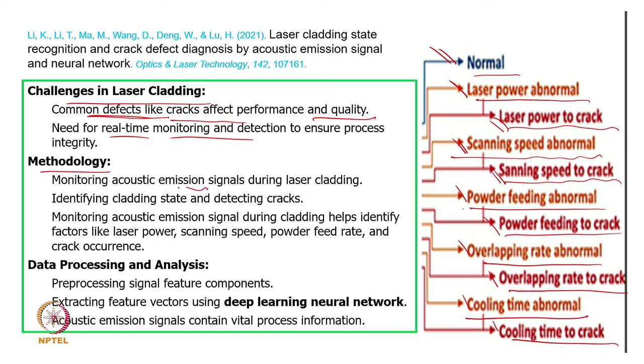Basically, we try to capture acoustic emission signals, and then based on that we divide into two categories. One is detecting cracks. The other is the cladding state: what process is happening, and whether we can use or improve the process parameters. When you are monitoring the acoustic emission during the cladding process, it helps us to optimize the laser power, the scanning speed, the powder feed rate, and also minimize crack occurrence.